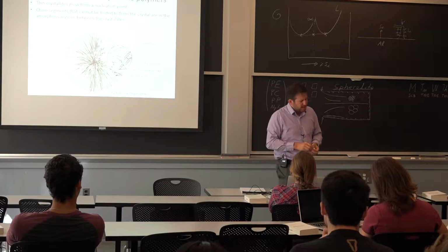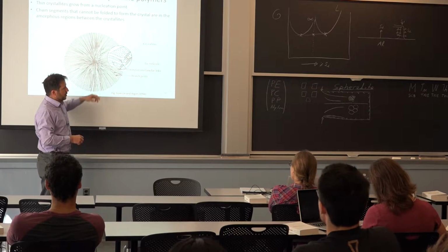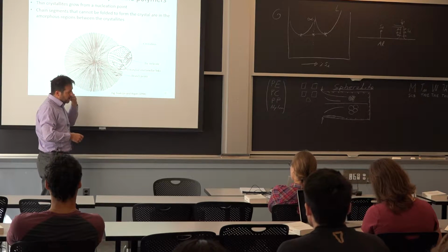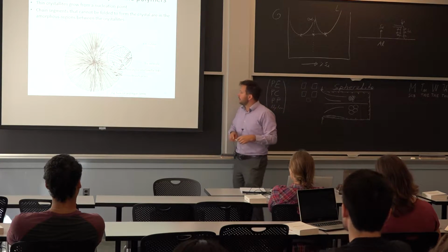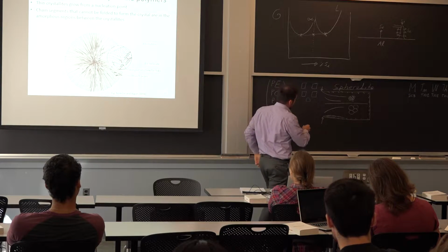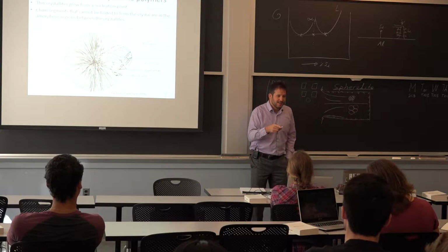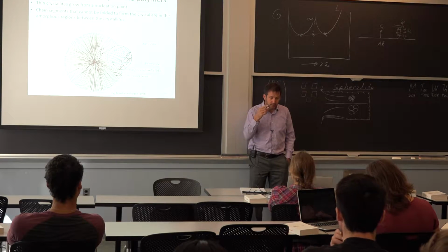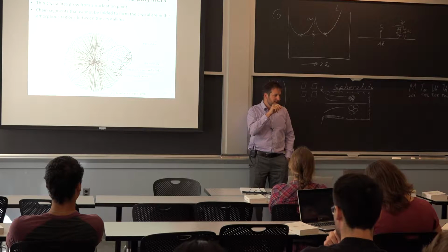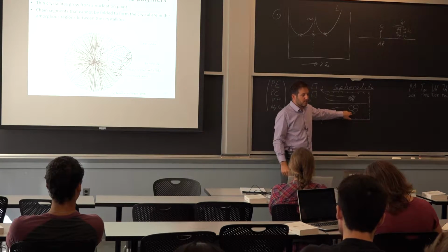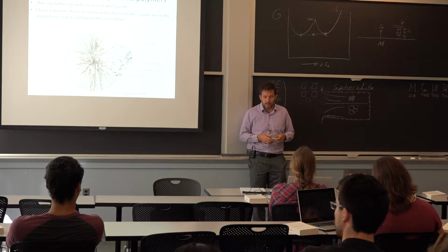All right. So it's different because now we're dealing with a different process here of forming our solid. This polymer solidification doesn't really lend itself to issues of segregation, except that between the dendrites, you can have a little bit more of the impurities. What I'll say to counteract that is, sometimes you put in a nucleation agent, so you put very, very small particles that will be the center of your spherulites. Because they're big enough, they're not going to end up in the corner because they are the origin of why you had the nucleation. And that's the same process of heterogeneous nucleation where you start from something as opposed to having to build up from scratch.